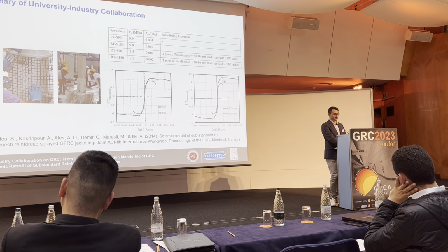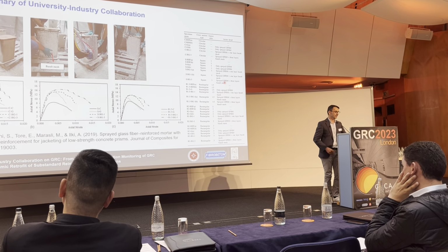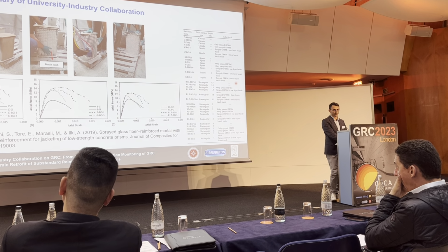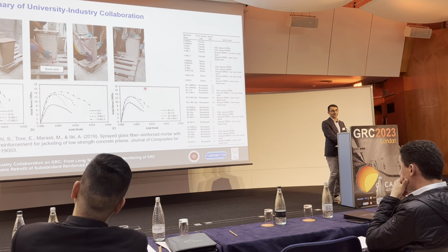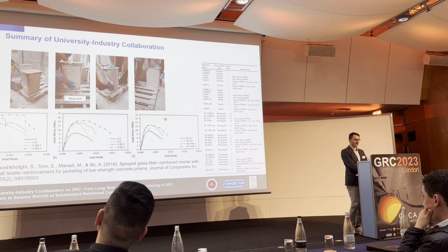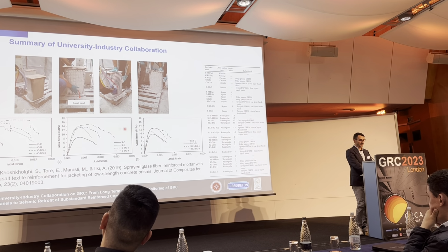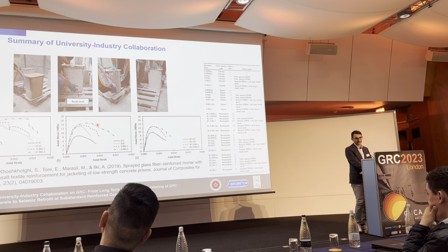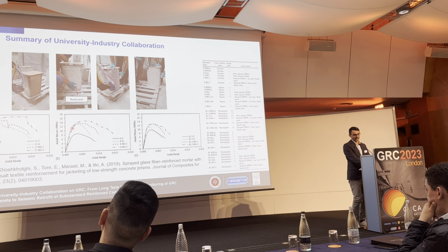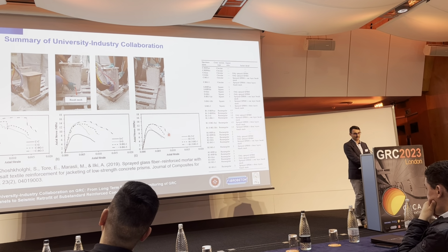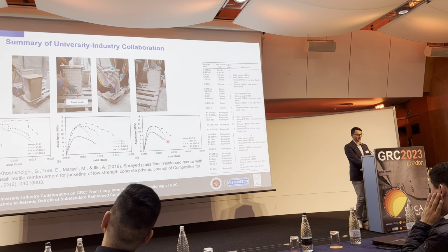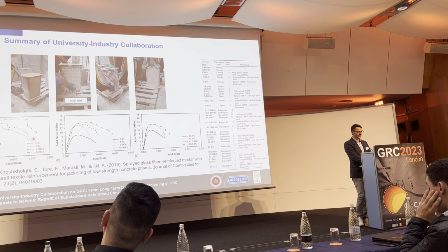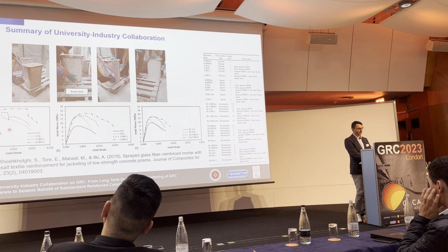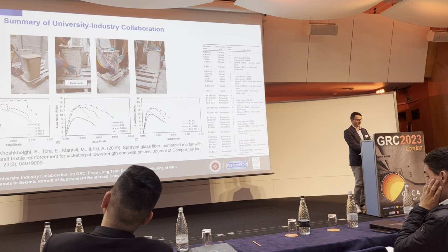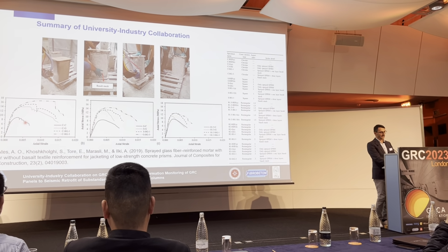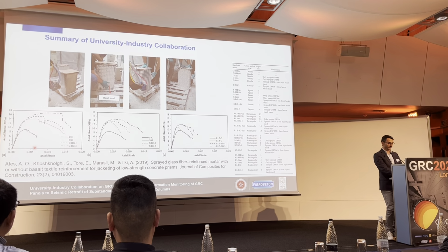After conducting this pilot study, we decided to enhance our knowledge of this methodology. First, we needed to model the behavior of the confined, jacketed concrete, so there was a need to make some confined concrete tests. As you can see here, we conducted uniaxial compression tests on square, rectangular, and circular cross sections. These again represent low strength concrete, which is a general property of the existing building stock in Turkey. On the left-hand side, you see the result of the circular specimens. This one is the reference with a compressive strength around 9 megapascals, and the ultimate strain corresponds to 5 per thousand or so.